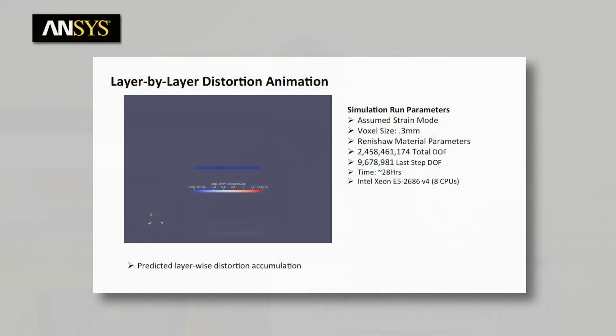And so here's the first set of results. If we animate layer by layer what's going on with this complex part, we start out blue again is least distortion. The dark red is 1.4 millimeters of distortion. Remember, the blade is 1.3 millimeters in thickness, so we've actually moved the blade more than its entire feature thickness if it gets to that level.